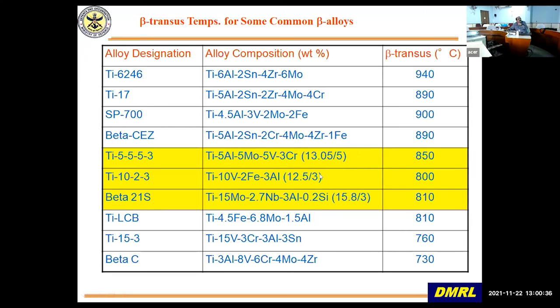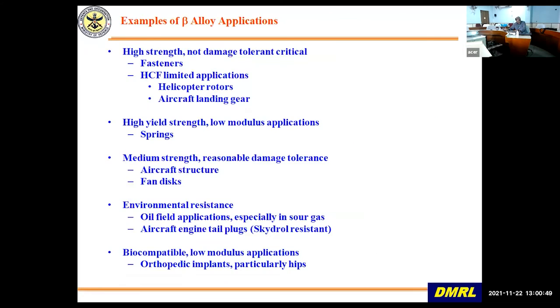And this is beta 21s. This is a sheet alloy, very good for sheet applications. And there are other compositions as well. You can see the beta transus temperature of these alloys is much lower compared to near alpha titanium alloys, which is normally around 1000 or more.